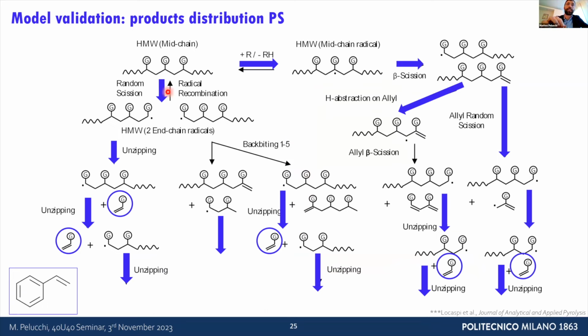Why am I getting only a monomer from polystyrene? If we get back to that radical chain mechanism that I've shown in a general fashion before, and you think about G now being an aromatic ring, phenyl, C6H5, if you do a random scission on polystyrene, you get a radical at this point. This is a resonance stabilized radical that will break by beta scission with this bond. So you have this unzipping reaction that releases a monomer, which is this double bond with the G attached.